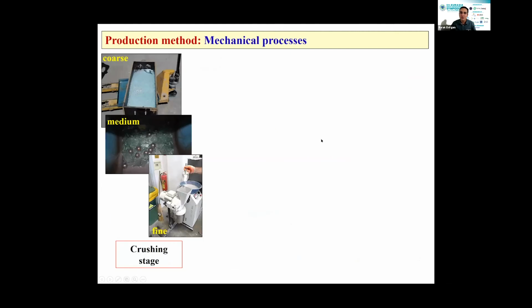And this is the production method. The first stage of the production method is the mechanical processes. As I said before, this is the production of type 2 glass powder. We take our broken glasses from our university and break them into smaller parts with a hammer. Then we put them into the Los Angeles abrasion machine. As you know, we generally use the Los Angeles abrasion machine for concrete or asphalt pavement elements to determine the abrasion value.